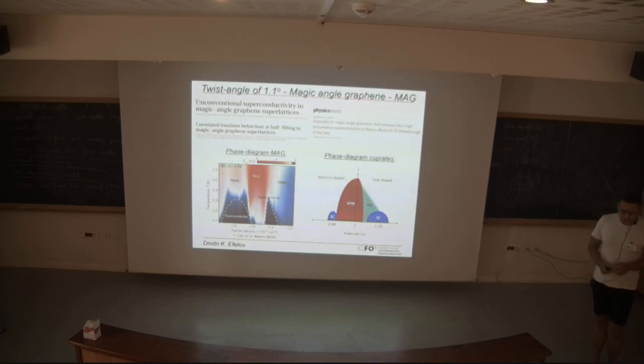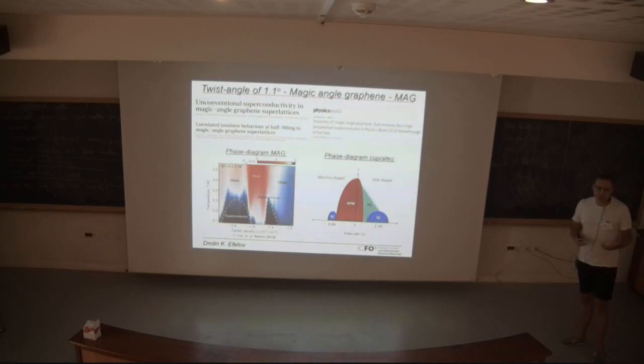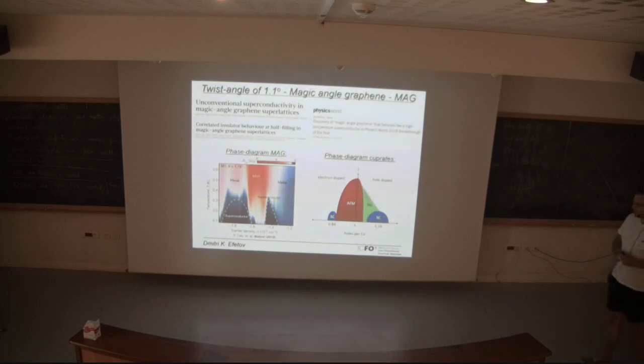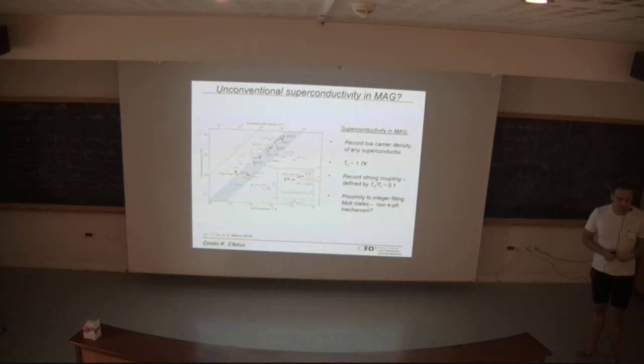This is the phase diagram in graphene. As you can see, as a function of temperature and carrier density, basically doping levels, it was reported that there is a Mott-like insulating state around half filling of the Moiré band structure. If you tune slightly to the electron side or to the hole side, superconducting regions appear, and these are also dome-shaped. Of course, immediately there was a lot of excitement because people started comparing those two systems. Naively, the idea is that potentially the mechanism governing the superconductivity in those systems is similar. I'll touch base on where the discussion went from there, because this is a highly debated topic right now.